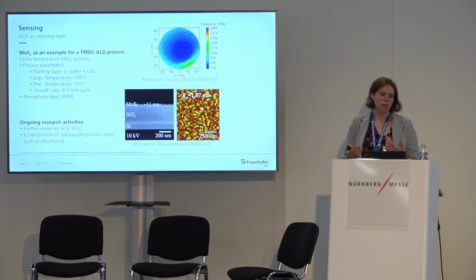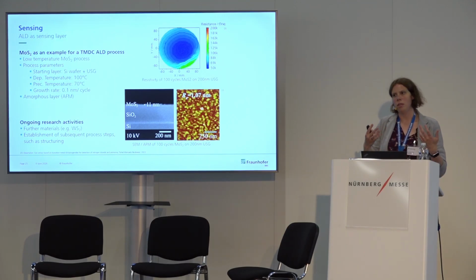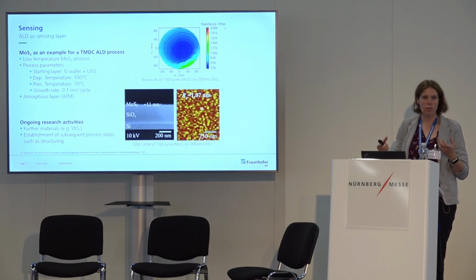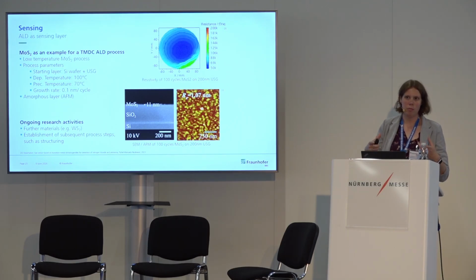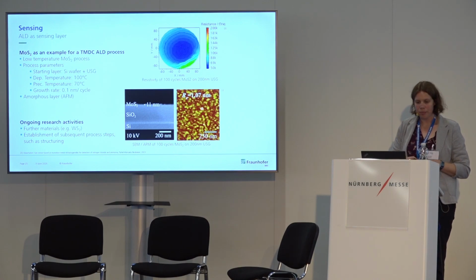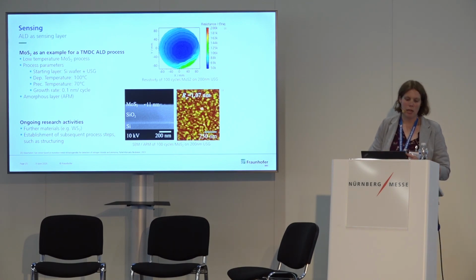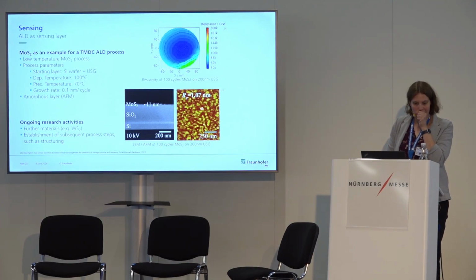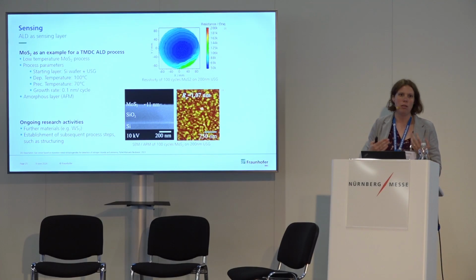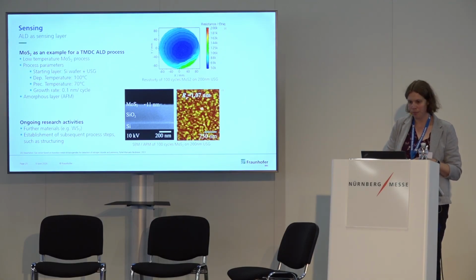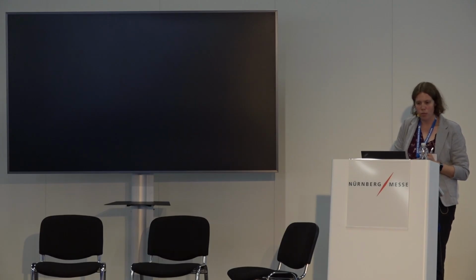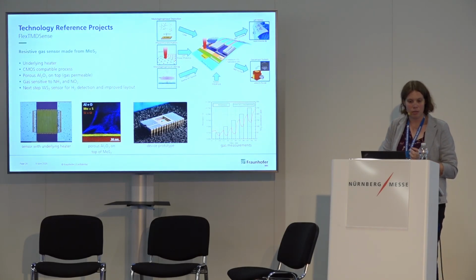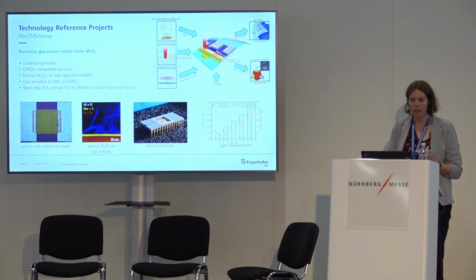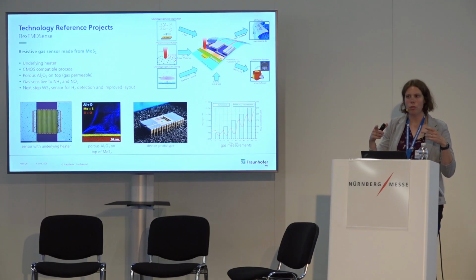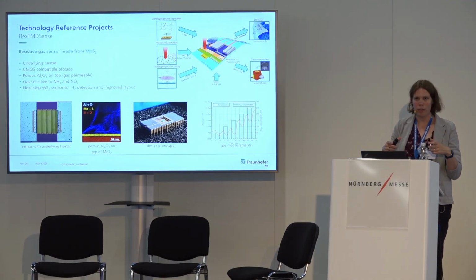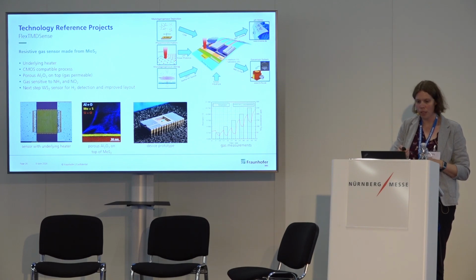So here there are also ongoing research activities. I mean, on one hand, we can deposit it, but if we have deposited on a full wafer, then the next step is that you want to structure it. And this is not as easy. So here are our ongoing research processes to establish litho processes and also etching these materials. These materials were used again in a gas sensor. It was a resistive gas sensor, and the specialty here was that we do not use rigid silicon wafers, but that we used a flexible foil for this.